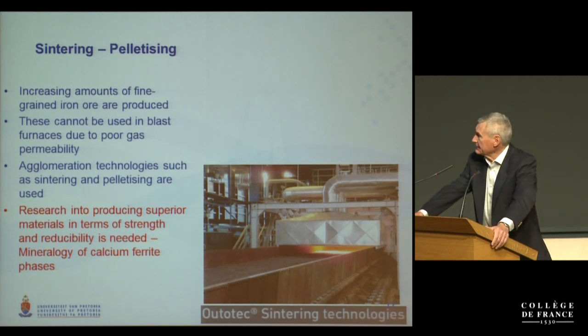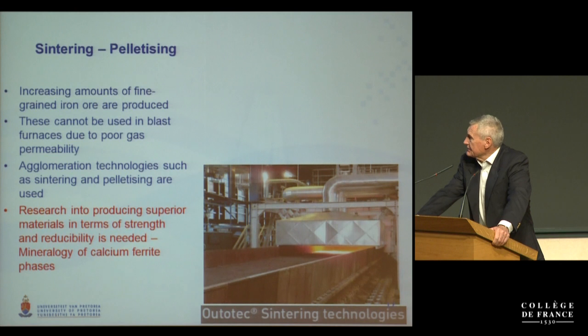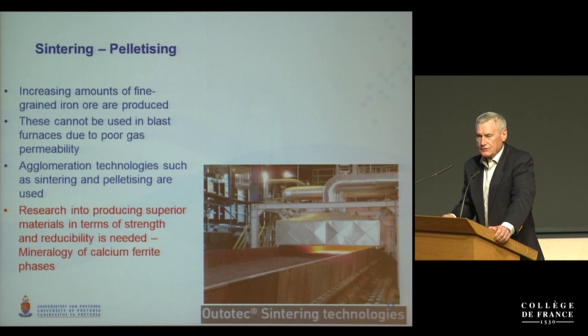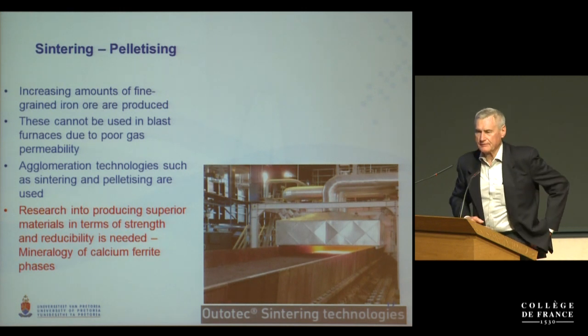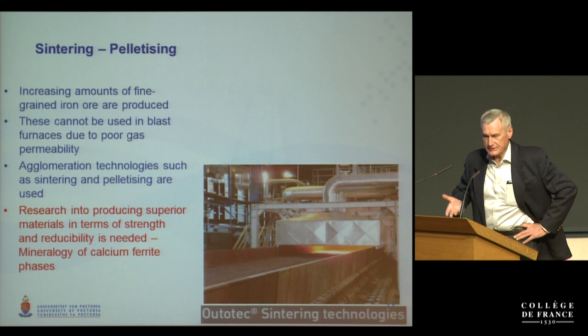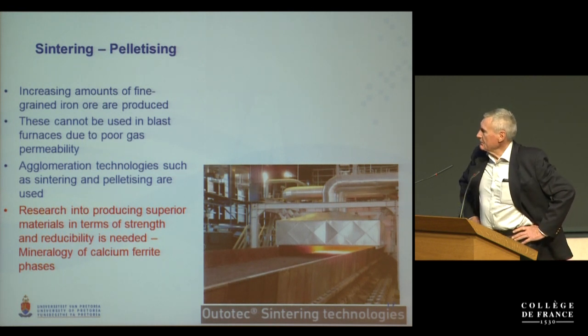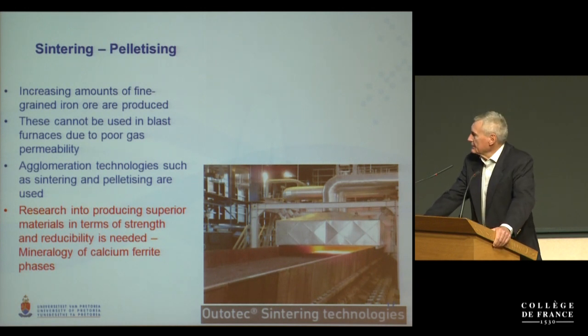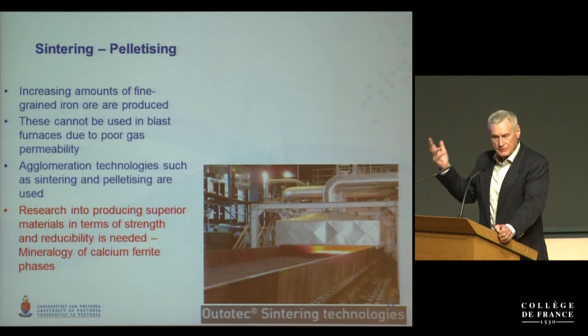Another one is sintering and pelletizing. Because of the fact that increasing amounts of fine-grained iron ore and fine-grained manganese ore are produced, they need to be agglomerated because you cannot use a fine powder in a blast furnace. It inhibits the upward movement of gas, CO gas, which is necessary for pre-reduction. So you need an agglomeration technology, and the two main technologies are sintering and pelletizing. And there's been a lot of work on producing superior materials in terms of strength and reducibility. It's much more reducible, for instance, than pure iron ore.